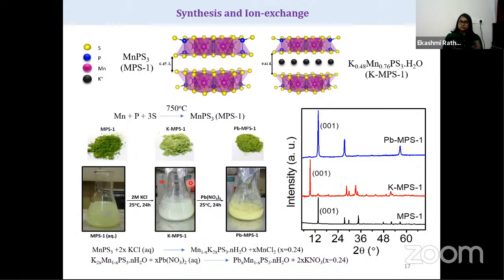For all the lead sorption studies, I prepared artificial solutions using lead nitrate. Here you can see that there is a color change. This is a powder X-ray diffraction pattern, where the 001 peak corresponds to the layered peak and tells us about the layer spacing. When I intercalated potassium, the layer spacing increased and the peak shifted to the left. When I treated it with lead nitrate solution, it shifted to the right. So it tells us that ion exchange is happening.